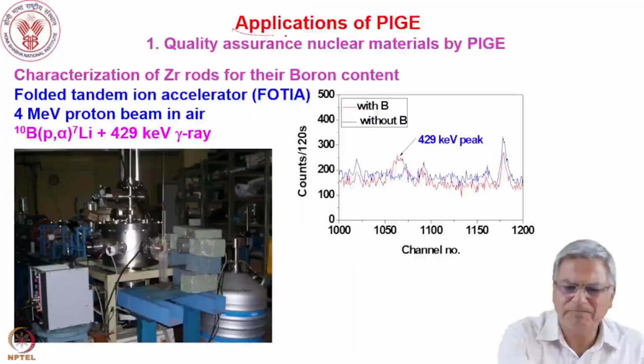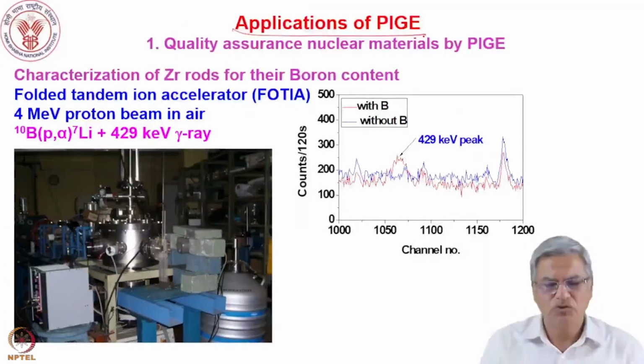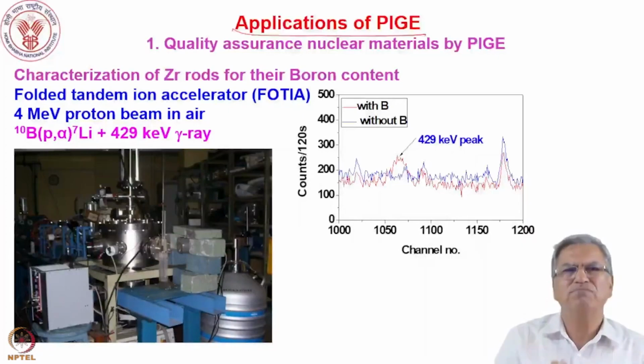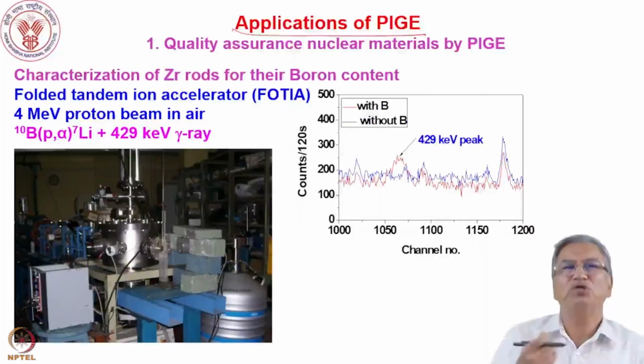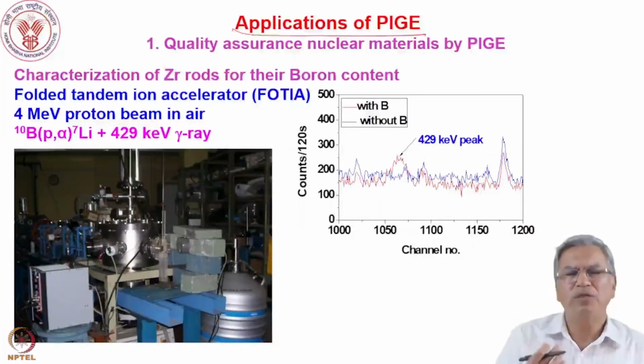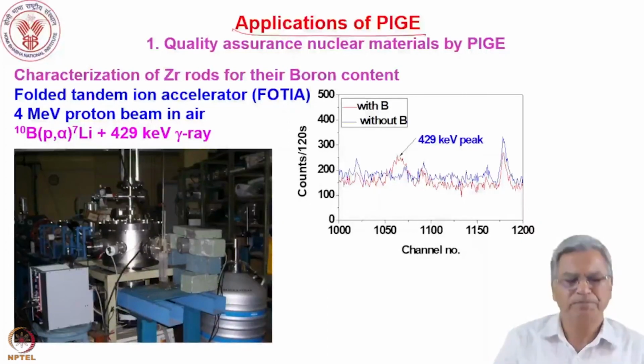So PIGE is a very simple technique. You are not going to use it for depth profiling because you are using protons, so the stopping power is not very high, and the resolution is not good. As I mentioned in RBS also, for the 4 MeV proton beam, the resolution was 1 micron. Normally, you would look for a nanometer scale depth resolution to do depth profiling.